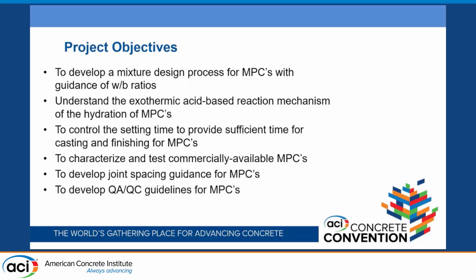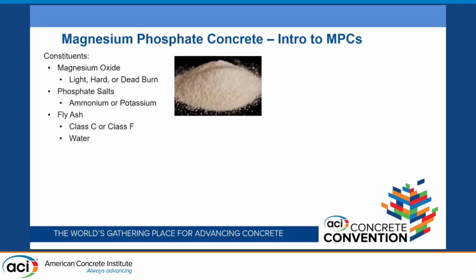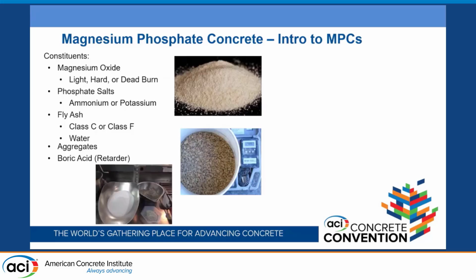And then the ultimate goal, which we're still working on, is to eventually develop QA/QC guidelines for magnesium phosphate concretes, and also develop airfield construction specs. So we're getting there. So, intro to the MPCs: this is the binder portion of it, magnesium oxide and phosphate salts. Those are your main two binder materials. That's what forms your acid-base reaction. And then you have a fly ash, and the fly ash helps with the reactivity, but its main purpose is slowing that reaction down without degrading strength. And then you also have water, and you add your aggregates, and you get concrete. Boric acid is the most common retarder used in MPCs, but there's some caveat with the boric acid that I'll get to in a bit.